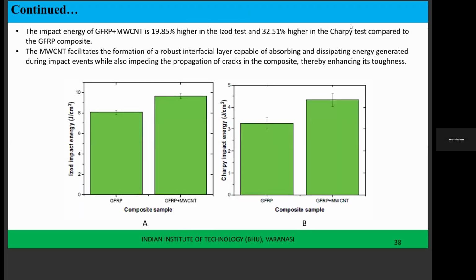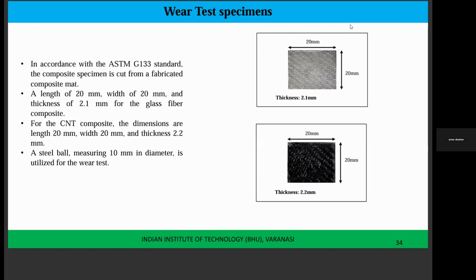You can see that for the Izod case, the impact energy is higher for the multi-walled carbon nanotubes mixed with the GFRP polymer composite. Similarly, for the Charpy case also, the coating is always increasing, enhancing the property. Next slide, please. We have also performed the wear test and observed the coefficient of friction as well as the wear rate. Next slide, please.